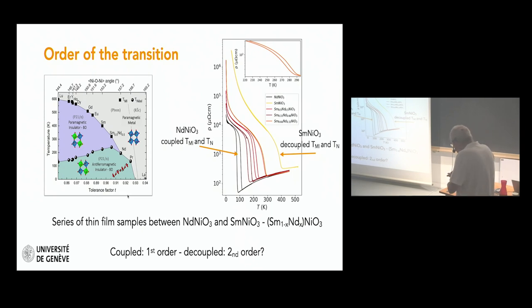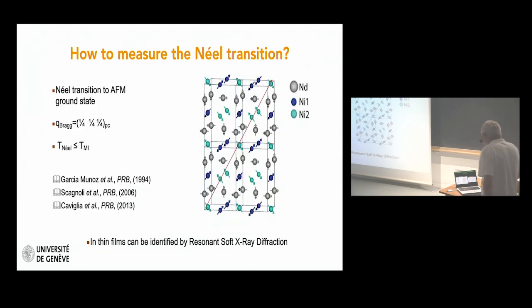But there is something I forgot to mention, and it's good that you asked a question, is that if you look at the hysteresis width, you see that this hysteresis width is going down as you go up and up in temperature. And so it is well possible that, in fact, samarium nickelate also has a first order transition, but you do not detect the width.